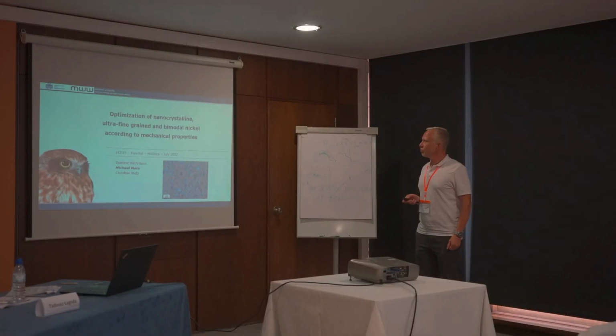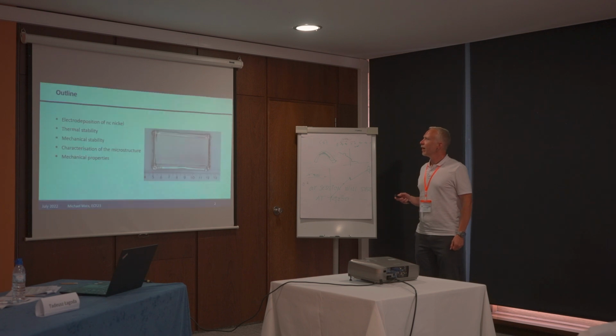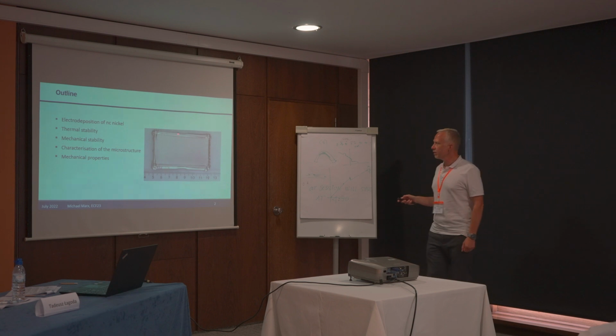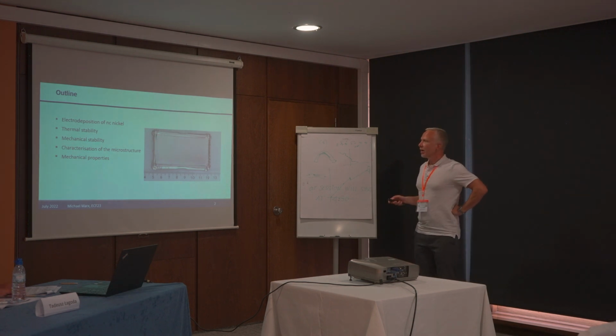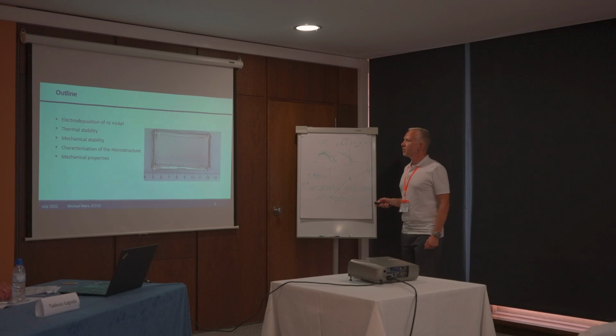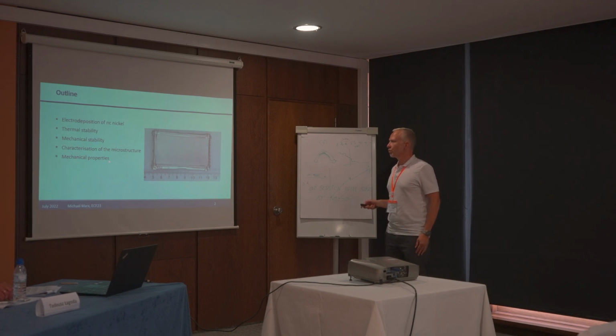We are working on nanocrystalline and ultrafine grained nickel, and what we do, we make electrodeposition of nickel. Here you can see such an electrodeposited plate, and then we investigate the thermal stability against grain growth, the mechanical stability, we characterize the microstructure, and we are interested in the mechanical properties.